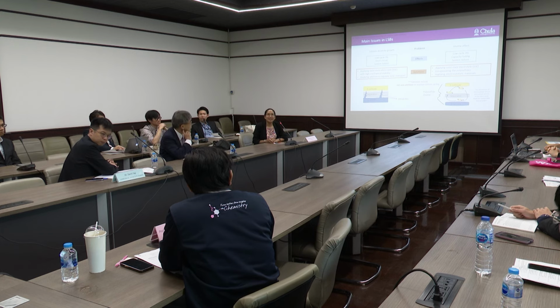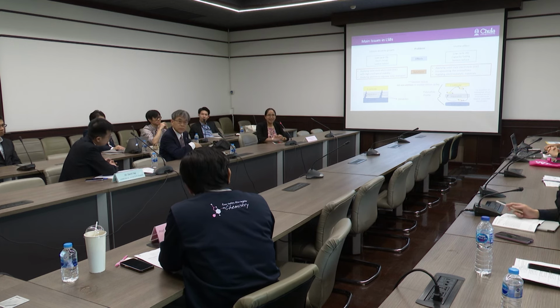Any other questions? If not, I may have some questions. So your first work is based on simulation. Did you do experiments? Yes, we also did some experiments, but that work was done by NTech. Did it give results in agreement with the MSO calculation? Yes, the MSO is better than the other co-solvents at this ratio. We did not do all ratios. We just compared at 25% with four co-solvents, and the MSO showed the best performance. So you did just one. Yes.